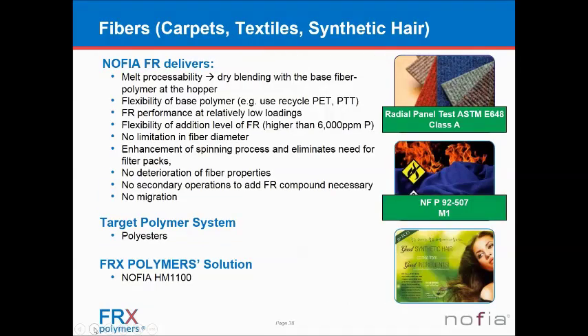So one of the bigger examples where we are being used, like I mentioned, is in fibers. That's going to be carpets, textiles, and synthetic hair. And one of the big advantages is that you can use our material and dry blend it with the base fiber polymer at the hopper. So you have a lot of flexibility on which type of polymer you want to use. You can have a lot of flexibility in the amount of phosphorus that you want to add to your fiber applications. And because we are polymeric, you have no limitation in your fiber diameter. So you can spin very thin fibers, which is typically not possible if you have, for example, a non-meltable flame retardant, which will give rise to a lot of fiber breaks when you apply those types of materials.